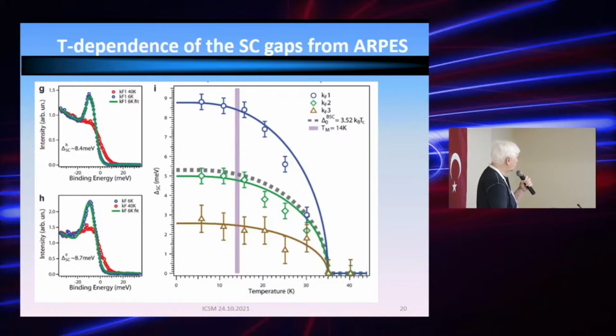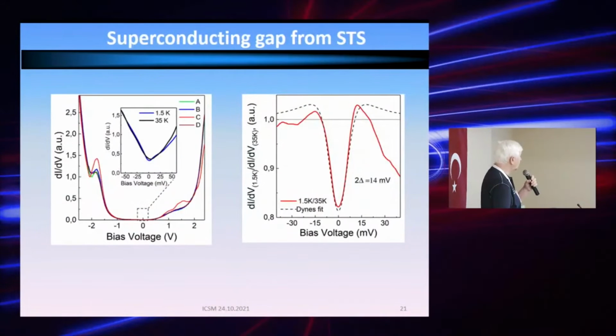And we have to apply other instruments to see the potential coupling between magnetism and superconductivity. So we do scanning tunneling spectroscopy. Since the sample is cleaved under high vacuum at low temperatures, it exposes the rubidium surface, which is 0.6 nanometers away from the superconducting plane, so it is hard to even anticipate seeing the true superconducting gap.